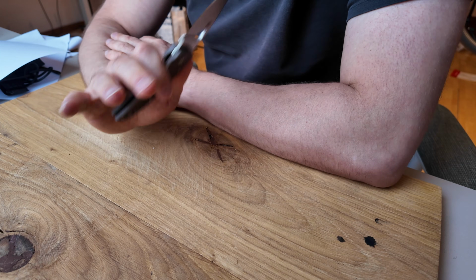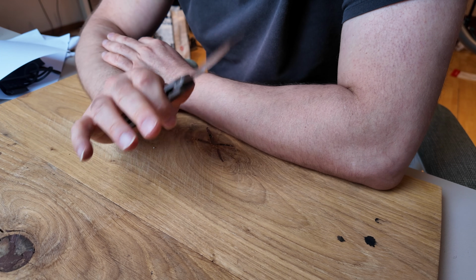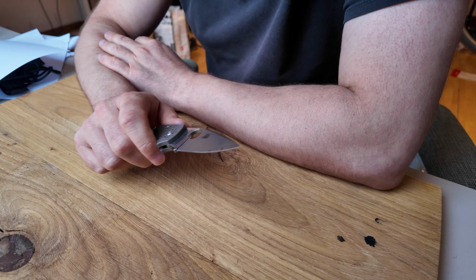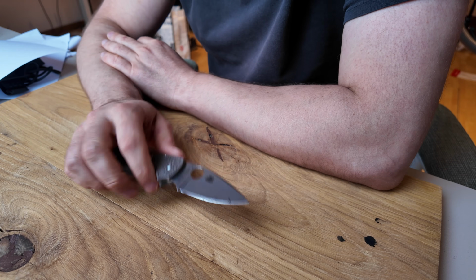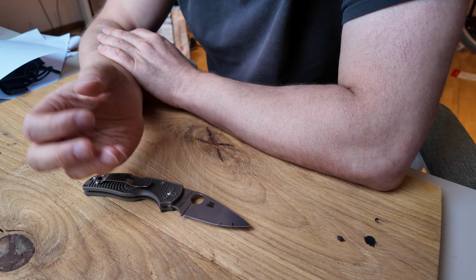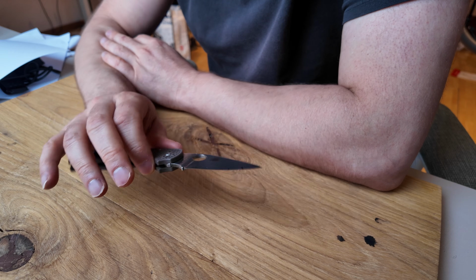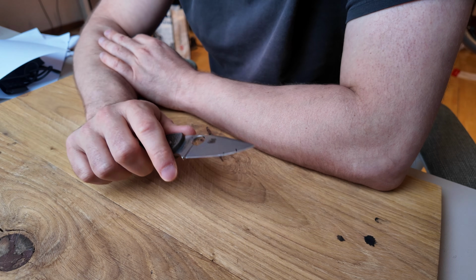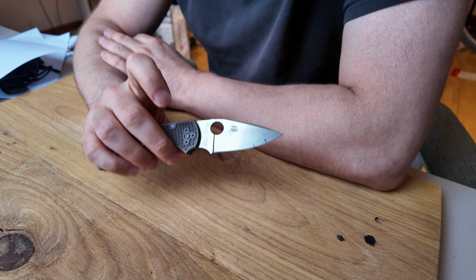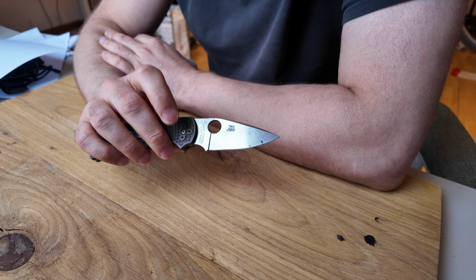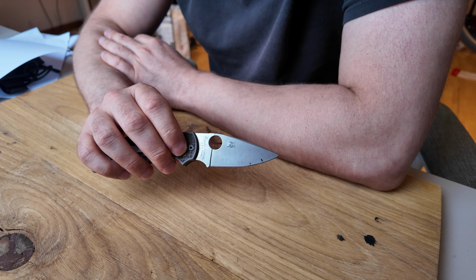Vanadium carbide sits at 2800 Vickers and aluminum oxide at 2000. A waterstone is not cutting those carbides, it's cutting everything around them. So what does an apex full of exposed carbides do when you actually use it? I put the Spyderco Native 5 in CPM 15V and the microscope to work to find out.